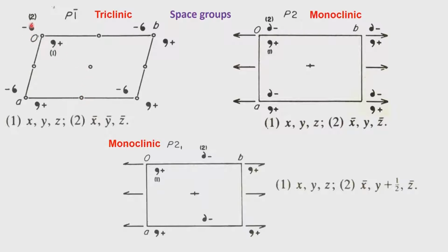And as a consequence of that, this symmetry operation which goes outside of the unit cell can be brought into the unit cell by one unit translation along A, one unit translation along B. So, it is actually representing two such units, two such objects in the unit cell. We call them the number of molecules or whatever, number of units, number of objects inside the unit cell. In this case it is 2.